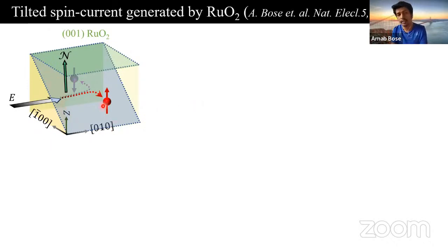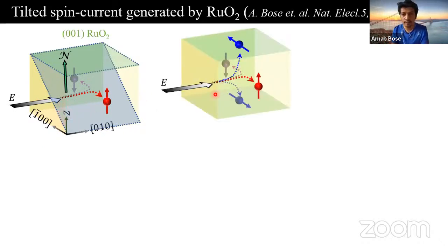Current flowing along X, spins are flowing along Y with spin polarization along Z. But there is a difference. For the spin Hall effect, spins flow in all the planes equally, as shown here, which is forbidden for ruthenium dioxide. For example, in this case, we cannot have the spin current flowing out of the plane, meaning we cannot have spin current flowing in the 001 axis, because it is prohibited, because the Néel vector points in that direction. So this is fundamentally different from the regular spin Hall effect.